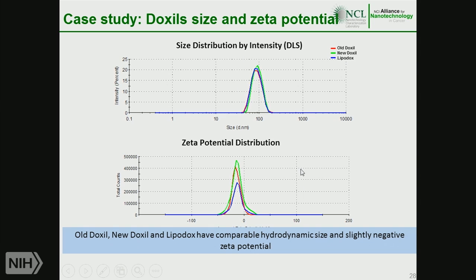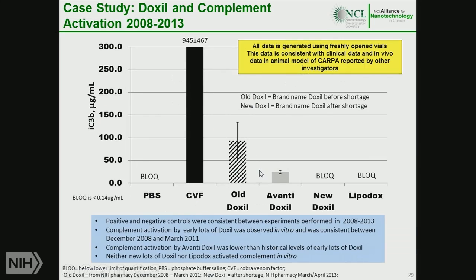The important message from this slide is that there is no difference between these formulations in size by DLS and zeta potential. But let's look at its biological reactivity. According to the literature about clinical use of Doxil and also animal studies in pigs model of CARPA, many investigators reported that the old Doxil is inducing complement activation and complement activation related to the allergy. And you see this in vitro assay data are in agreement with those observations. However, new Doxil and Lipodox do not have this toxicity, which again correlates with the clinical observations.